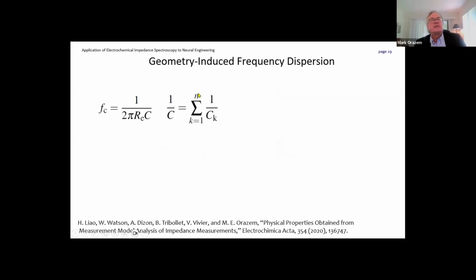Let's talk a little bit about the geometry-induced frequency dispersion. So there's a characteristic frequency that we can calculate that's based on the ohmic resistance and the capacitance. And this capacitance is extracted from the measurement model as a sum, 1 over C is equal to the sum of 1 over the constant capacitances associated with each of the Voigt elements.